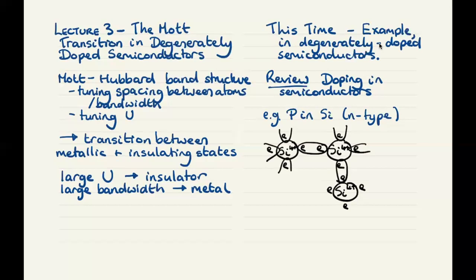When we put in a phosphorus atom instead of a silicon, the phosphorus has 5 valence electrons, so we can treat that as a phosphorus 5+ ion with 4 valence electrons that form covalent bonds with the neighboring silicons, but then with 1 extra electron left over. And this extra electron will be somewhere in the silicon lattice, and bound to the phosphorus ion because the phosphorus is more positively charged than the surrounding silicons.